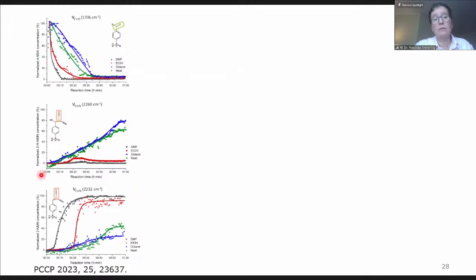Then we also monitored in which cases we observed the intermediate. And as we already saw before, that's for the neat grinding and the nonpolar solvent. Whereas in the case of DMF and ethanol, we did not observe any formation of an intermediate. And then we can see also that during the time span, in the case of the neat ground version or using octane, we were not able to reach a final plateau.